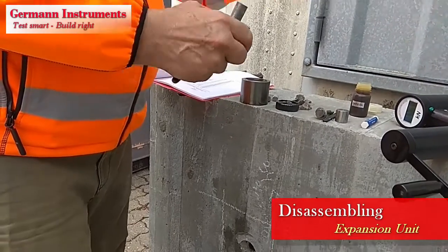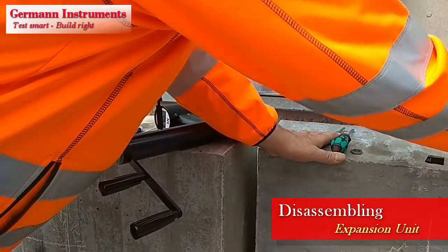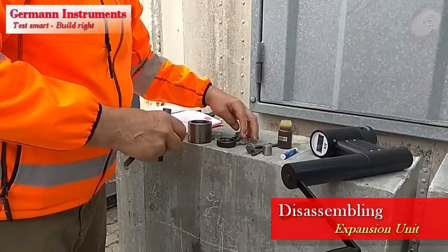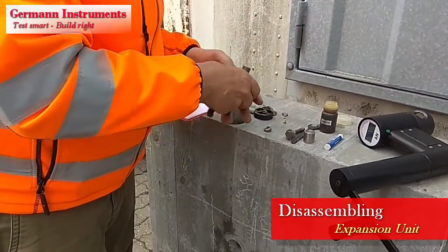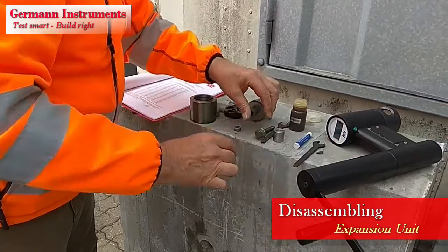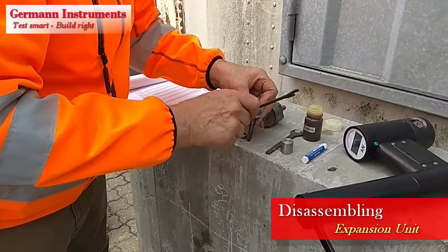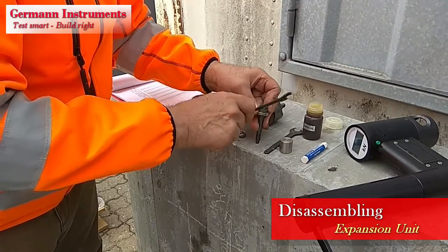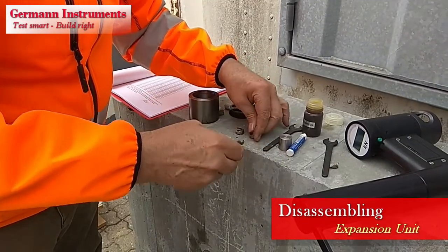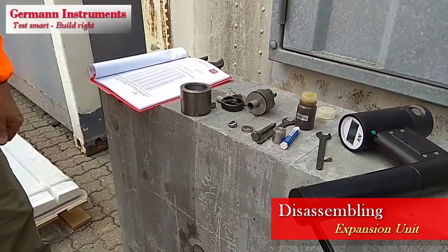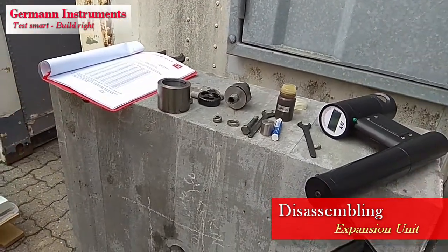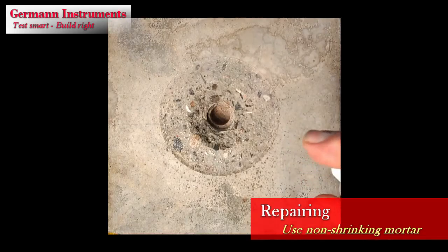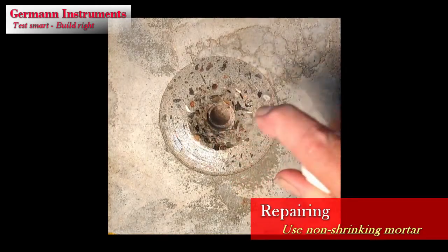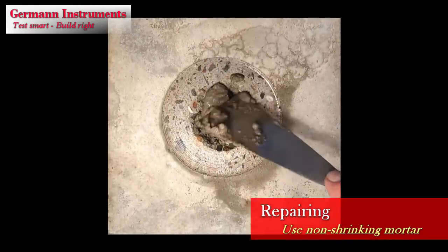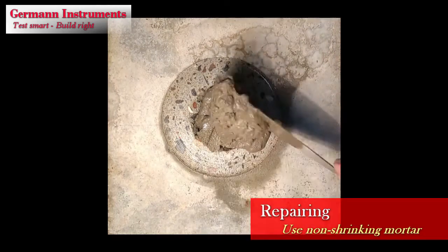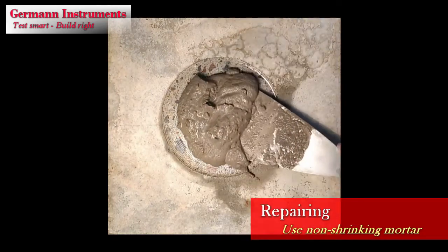To dismantle the expansion unit, use two 14 mm keys. Extract the cone and disassemble the parts. The expanded steel ring on the cone pull bolt is removed by light striking, the parts cleaned and oiled slightly, and assembled as shown previously. To repair the cone hole left in the concrete, apply a non-shrink mortar. First, spray the surface slightly with water, then mix the mortar and press it into the hole with a spatula. Smoothen the surface.